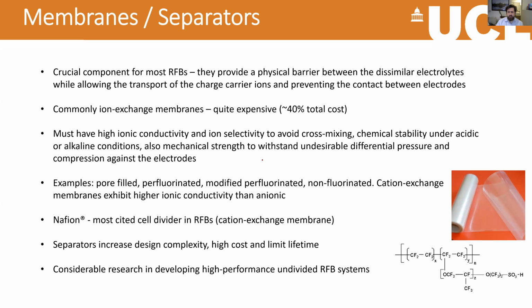I'll skip over the membrane separators because I'm running a little bit low, but essentially just to say we need a physical barrier there between the electrodes and also between dissimilar electrolytes. So these membranes have to be permeable to the ions that balance the charge, which normally in an acid electrolyte would be protons, but crucially have to try and limit the movement of the other ions in the active species. So in the case of vanadium, for example, we want to stop vanadium passing through. Those are positively charged vanadium ions, but allow positively charged protons to pass through, and that's quite difficult. And so there's lots of work into increasing the functionality of these membranes, but also in using membraneless systems, because sometimes they can be quite expensive as well, these things.